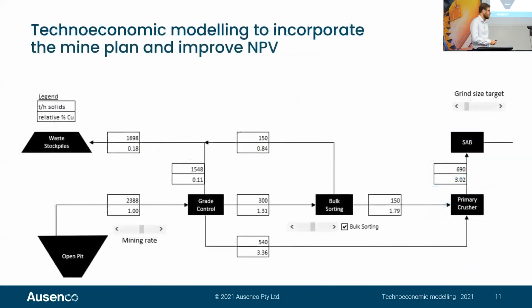You can then apply that to a technoeconomic model, which is kind of what you're seeing here, where we've got tons per hour solids and relative copper percentage. And you can see what happens in the grade control, where you're measuring over those 10-meter increments versus in the bulk ore sorting, where you're able to measure over smaller increments. You can then understand what grade is being rejected and what upgrade actually happens prior to the crusher and to the milling circuit.